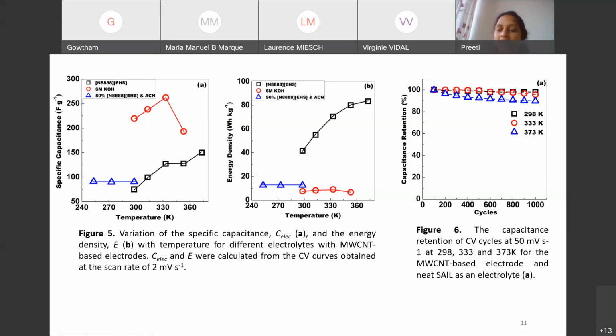But for neat ionic liquid it is 4 volt, which makes a lot of difference in the energy density, which is an important parameter for an electrolyte to be used in supercapacitor devices. Even though the specific capacitance is low, these values are at room temperature, so we can use it at high temperature with high energy density and high power density.